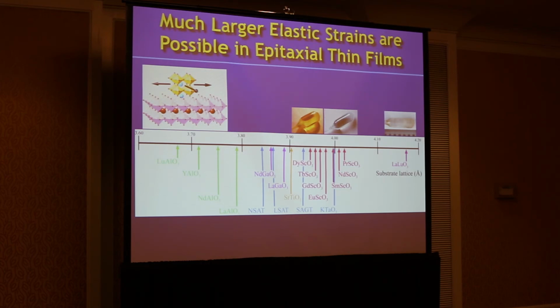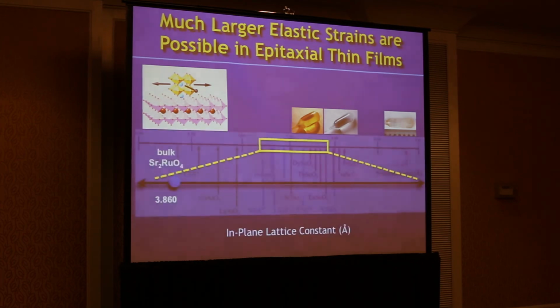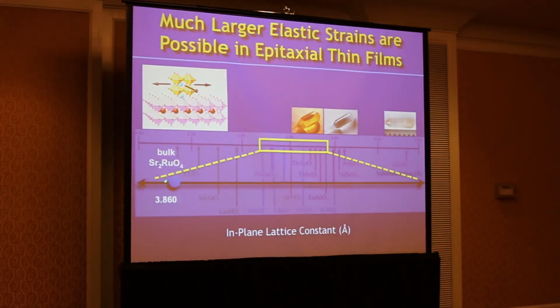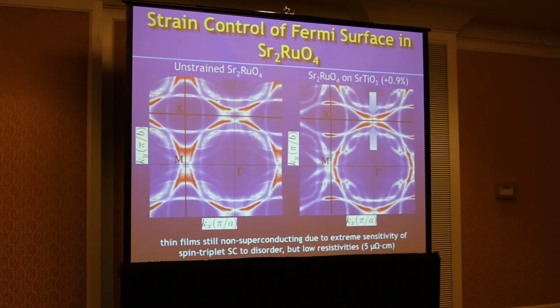So on this kind of a number line like I was showing you before, if we look at where bulk strontium ruthenate is in terms of its lattice constant, it's over here. And if we look at Andy Mackenzie's strained strontium ruthenate, he's strained it slightly uniaxially like this. But we can think of all sorts of bulk crystals to rain down the strontium and ruthenium on top of, in terms of changing the properties of the strontium ruthenate. So in this example, here you see our unstrained strontium ruthenate in ARPES, and here you see the strained strontium ruthenate in ARPES made possible by this approach.